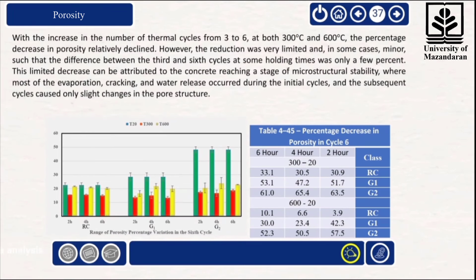With additional cycling from 3 to 6 cycles, porosity reduction at both 300 and 600 degrees Celsius decreased slightly. However, the reduction was relatively small and in some cases marginal, with differences between the 3rd and 6th cycles amounting to only a few percentage points. This limited change can be attributed to the attainment of a microstructural stabilization stage, where most evaporation, cracking, and water release had already occurred in the early cycles, leaving subsequent cycles to produce only minor alterations in pore structure. The table presents the porosity reduction percentages after 6 cycles for the 3 types of concrete.